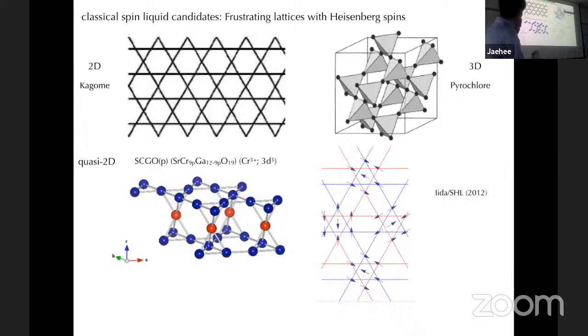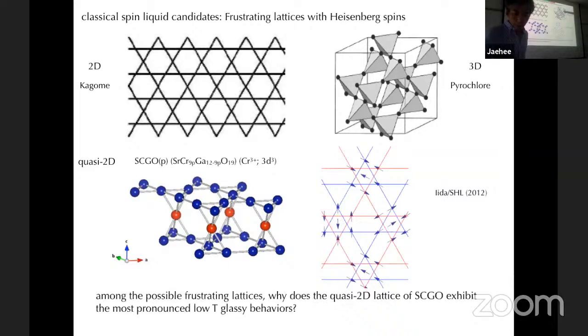All right. So now let me tell you a few classical spin liquid candidates here. In the two-dimensional case, the Kagome lattice, and in the three-dimensional case, pyrochlore, and the quasi two-dimensional one is this bipyramid case. So then one can ask why this is unique. Why does this quasi two-dimensional SCGO lattice exhibit more prominent glassy phenomena at low temperature than the two-dimensional Kagome lattice and the three-dimensional pyrochlore? The reason is the following.